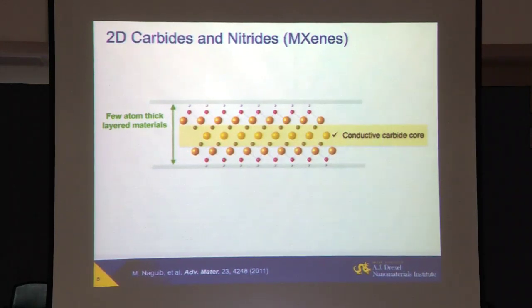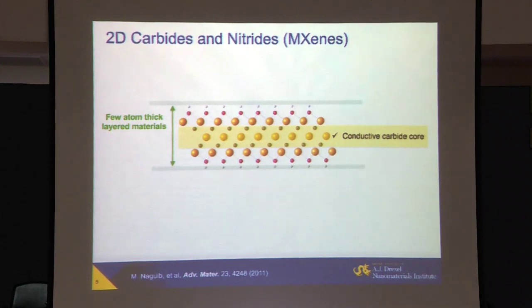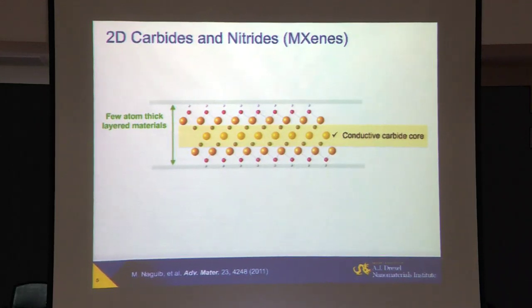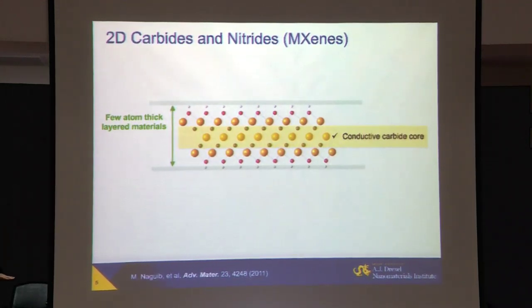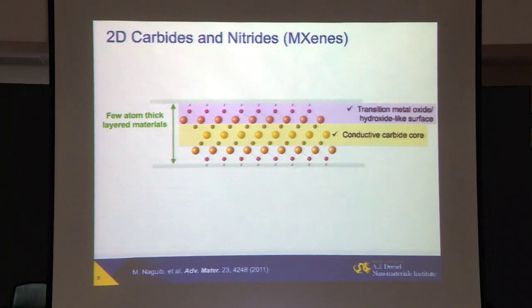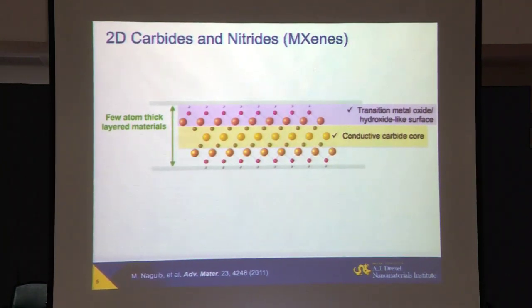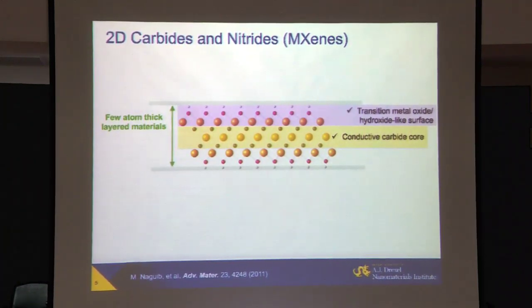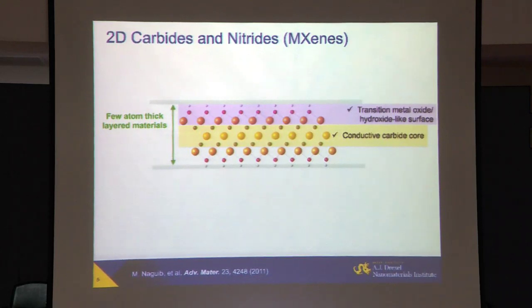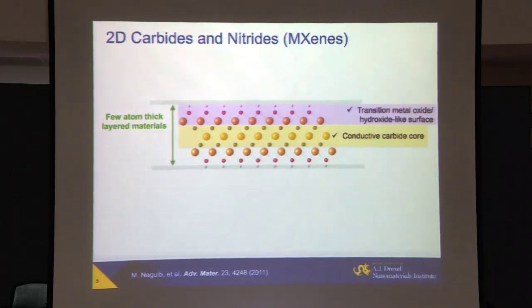So they are conducting inside, but on the surface, they look like clay or graphene oxide. But in graphene oxide, if you put functional groups on the surface, conductivity drops by several orders of magnitude. Moreover, their surface can be modified chemically without killing the conductivity of this material.